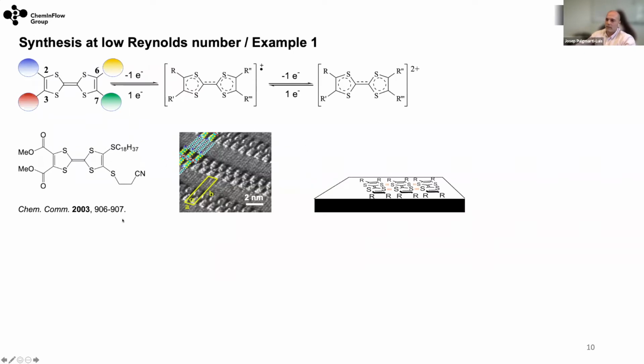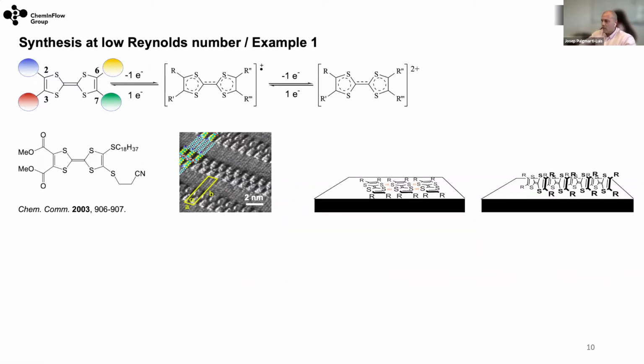And this is a paper they published some years ago, where they show that when you have a very long alkyl chain, what you see, this is the STM image. What you see here brighter is the part of the molecule that has the higher electron density. So this right part here is the core of the TTF. What you see in this case with these functional groups in these positions is that the molecule is lying flat on the surface. But what I told you is that for having a conductive material, it would be more interesting to have an organization like that, where you have a very good pi-pi stacking of the molecule so that it organizes perpendicular to the surface.